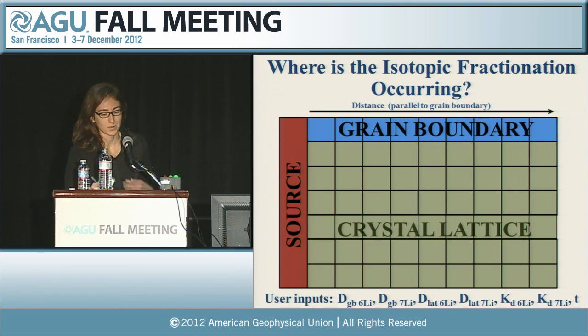So now I'm just going to show you some results of modeling that we've been doing to try and figure out where this fractionation is occurring. What the model space looks like is basically a source with a single straight constant thickness grain boundary perpendicular to that source. So this is very similar to the Fisher and Whipple-Le Claire type models. And the rest of the model space is crystal lattice. So the diffusant here can either jump from the source directly into the grain boundary or from the source directly into the crystal lattice. And it could also jump in between the grain boundary and the crystal lattice as long as it maintains partitioning equilibrium.